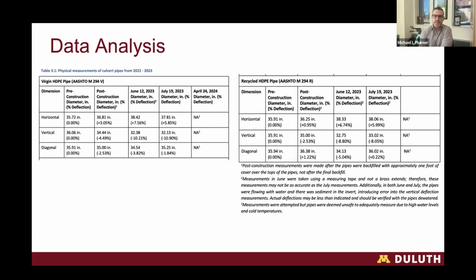But in this case, we're seeing greater deflections than we would have liked with the virgin pipe, especially. The recycled pipe was performing pretty well, but still, again, a little bit greater deflection than we would have liked. But the horizontal deflections were reasonable. The vertical were a little bit greater than we wanted. Again, I'm not confident of those deflection measurements though, given the sediment that was in the bottom of the pipe. So we're planning on going back into these pipes and dewatering them and doing a complete investigation once we get MnDOT's blessing to do so.